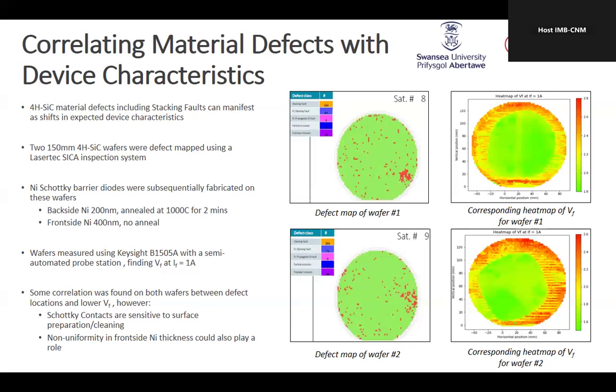But I think the issue we had here was that the Schottky contacts in silicon carbide are particularly sensitive, and the barrier height of those contacts is particularly sensitive to the surface preparation. And I think we can probably improve this correlation if we take care of the cleaning a little bit better in the future, or maybe use a slightly different cleaning recipe for the wafers. So this is something that we want to develop further, because we feel it can really help industry.